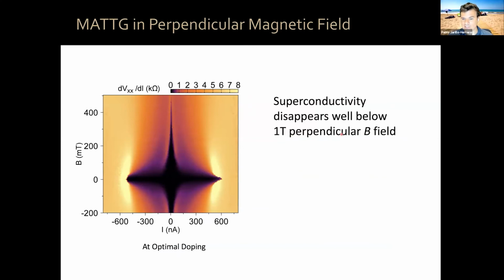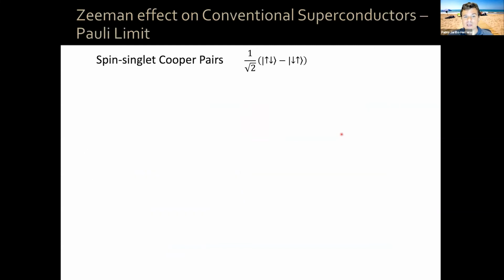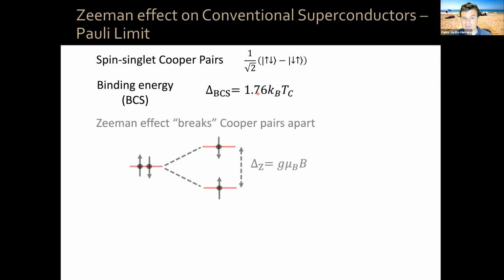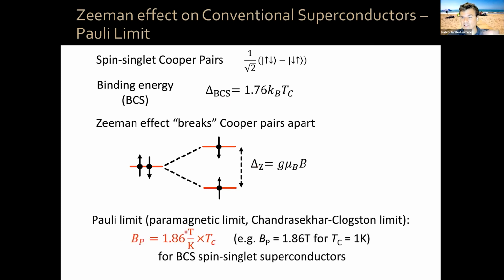Superconductivity disappears well below 1 Tesla in a perpendicular magnetic field. Magic angle twisted trilayer graphene, because it's a 2-dimensional superconductor, allows us to apply the in-plane magnetic field, where you don't have the typical orbital effects and vortex formation, and look at the effect of a Zeeman field. In conventional superconductors, Cooper pairs form spin singlets. They are bound by the gap. A Zeeman effect breaks Cooper pairs apart, spin up, spin down, so that by the time the Zeeman energy is equal to the gap, the superconductivity disappears.